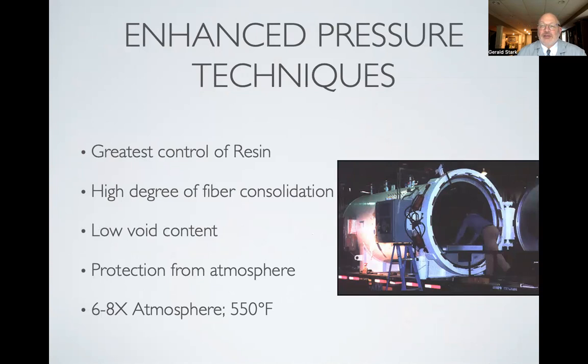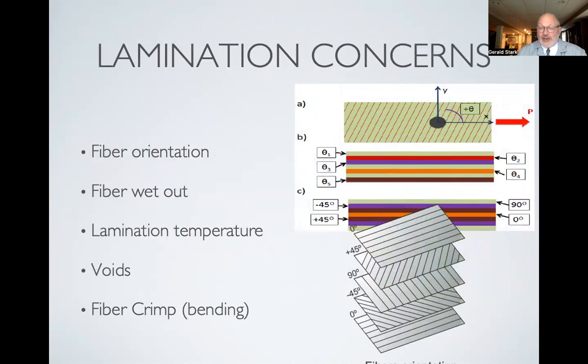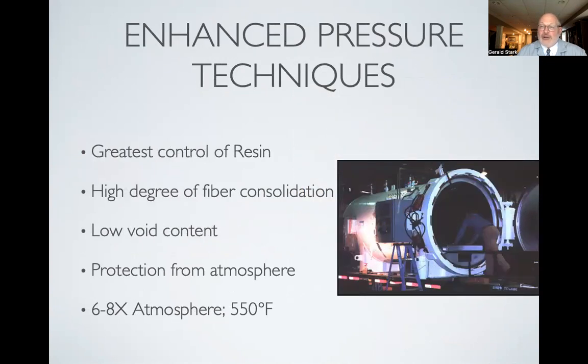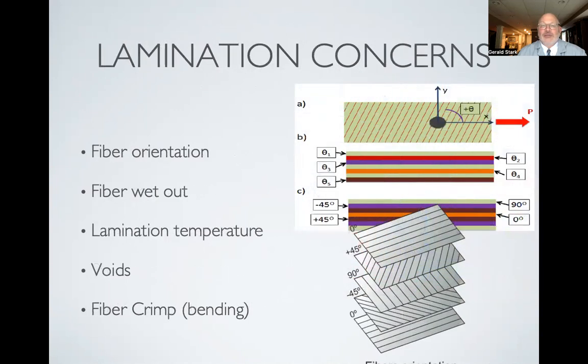As I mentioned before, it's typically 550 degrees at 6 to 8 atmospheres. And that's why we can't use plaster mandrels, or at least if we did, we could only use it once. But it's important that you have really no vapor, no water in that, because it creates bubbles within the system. So that's typically why aluminum is used. And so when we use prepregs, we try to make sure that we accommodate all the possible fiber orientations or resistances to the forces that we need to.